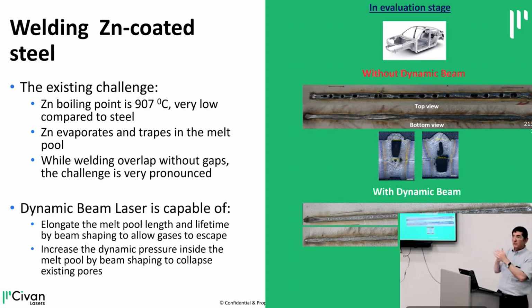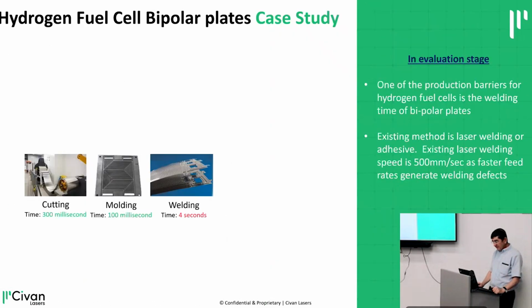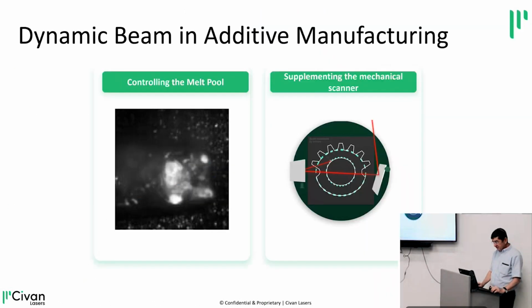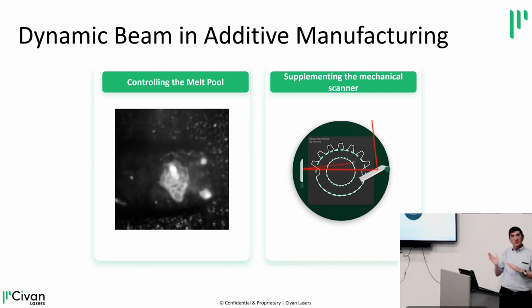So usually you have to do something about it, either take away the zinc or make some space between them to let the zinc go away. But we were able to show, by controlling the weld process, that we are able to weld these without having a space between them and without having the coating away. This is still in evaluation stage, but it looks very promising. Okay, so this was all about welding.